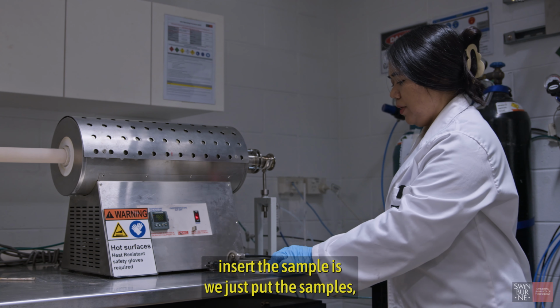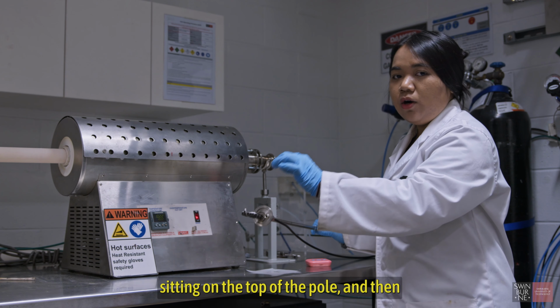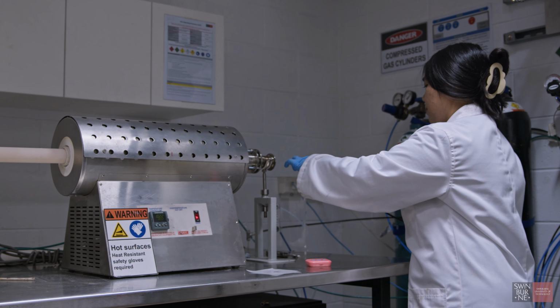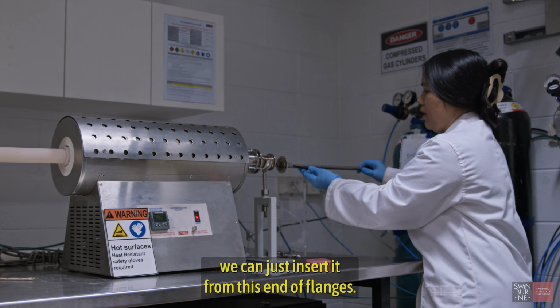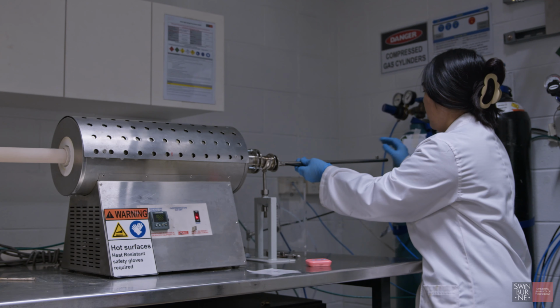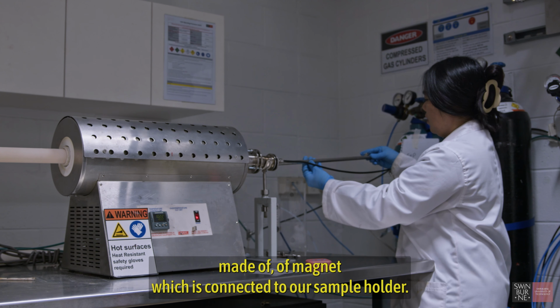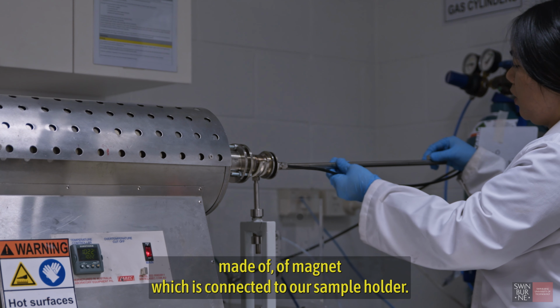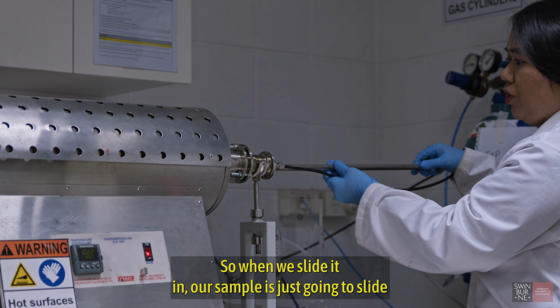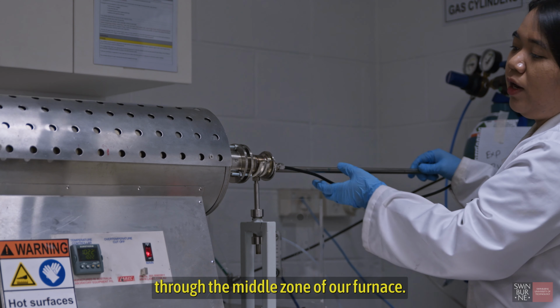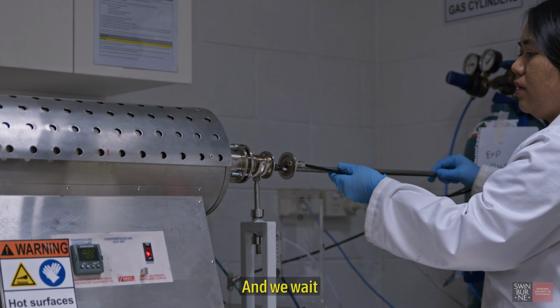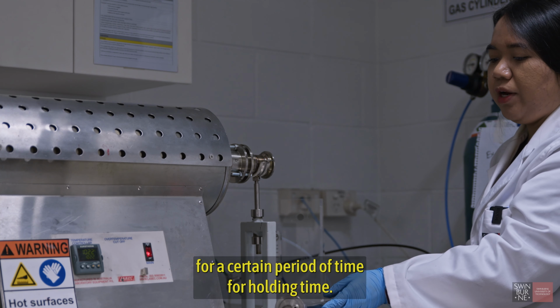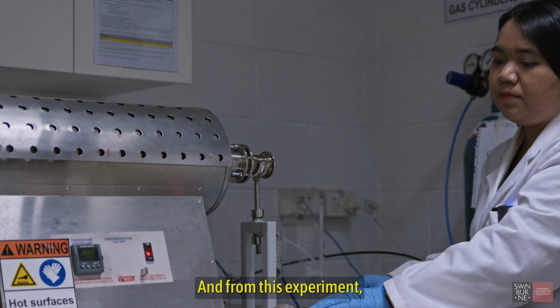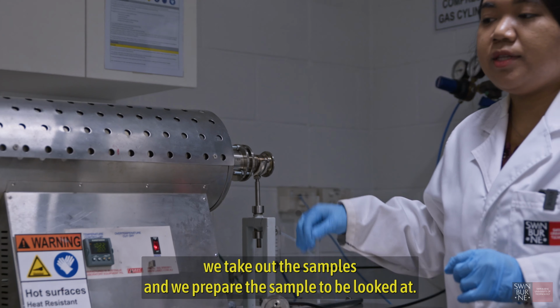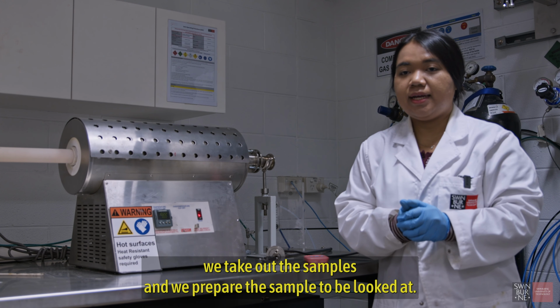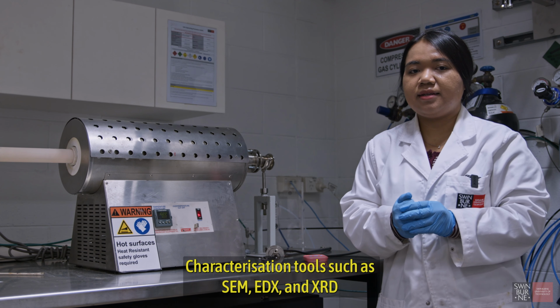The way we insert the sample is we put the samples sitting on top of the boat, and then we insert it from this end of the flanges. And there is a mechanism here made of magnet, which is connected to our sample holder. So when we slide it in, our sample is going to slide through the middle zone of our furnace. And we wait for a certain period of time for the holding time. From this experiment, we take out the samples and prepare them to be looked at with characterization tools such as SEM, EDX, and XRD.